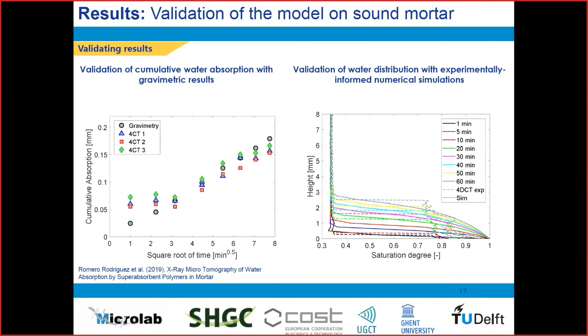So now the results. These are results for the samples that are not cracked. On the left graph, you can see that we also compare the CT measurements with a gravimetric experiment, which is basically measuring the mass that the sample acquires along the capillary water absorption. And you can see that after 10 minutes or so of water absorption, the results are quite close to